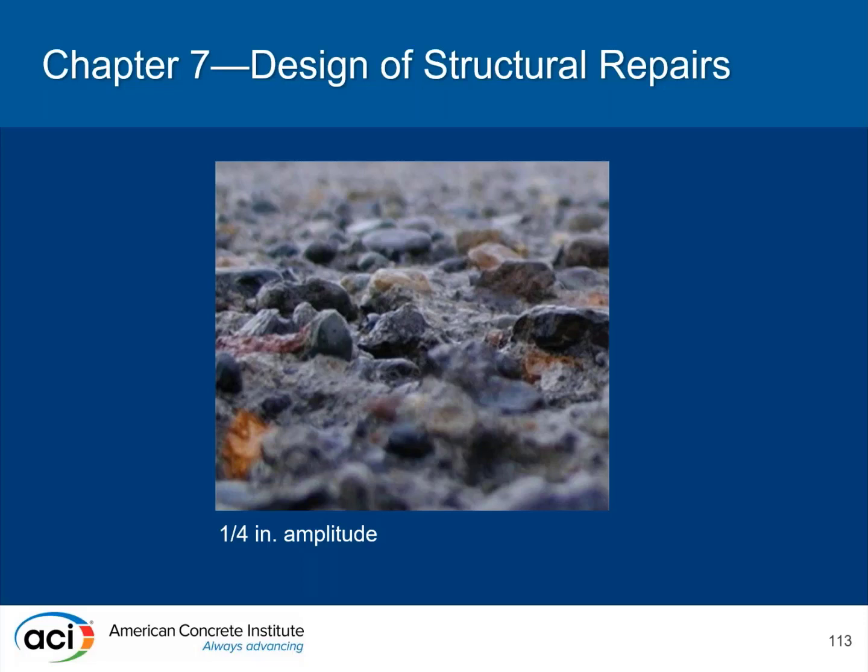So again, when that repair material is placed in intimate contact and scrubbed in or otherwise confirmed bonded to this surface, it creates a good surface for resisting those shear stresses that can develop. This is an example of a 1/4 inch amplitude, and in fact, with hydro demo, depending on the concrete, you can get even greater amounts of amplitude than is shown here.